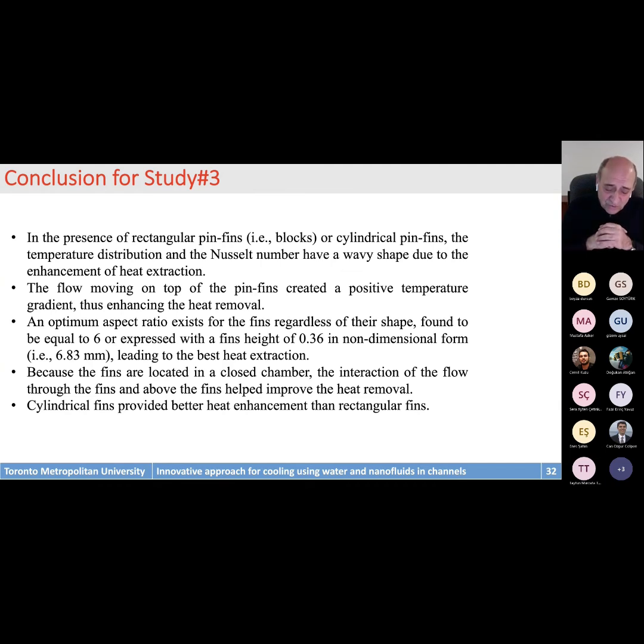And then what we also found when we looked very carefully at the data is that there is an aspect ratio for which the performance is better for one or the other. So basically, the height can help in creating a mixing between the flow going above the pin fin and the flow going between the pin fins and reaching to the top. This mixing can improve the heat extraction.